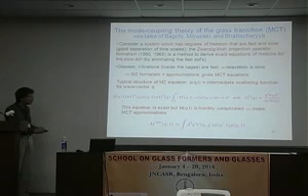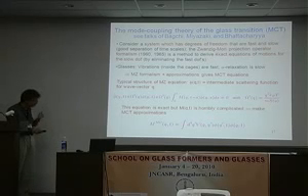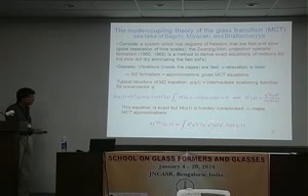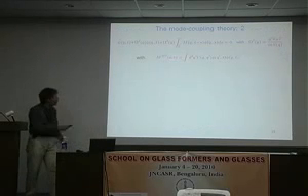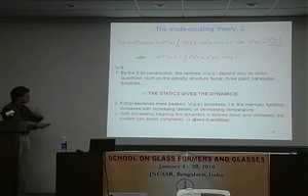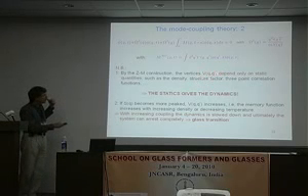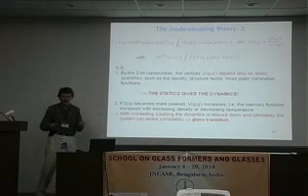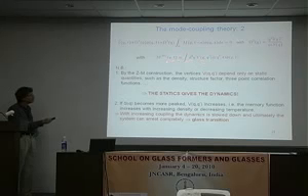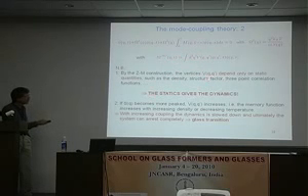So what you do is make an approximation, quite a strong one, which is quite uncontrolled, and you end up with something like this. Here again you have the correlation functions. So it's a differential equation in which this memory kernel involves, again, the time correlation function with certain factors. Now, what are these factors? I don't want to give the expression because the other speakers will probably do it. The only point is that this kernel depends only on static quantities, that is to say, on density, structure factor, 3-point correlation function, etc. If you replace the M by the M_MC, for mode coupling, which is an approximation, then if you know the static quantities, you get the dynamics.